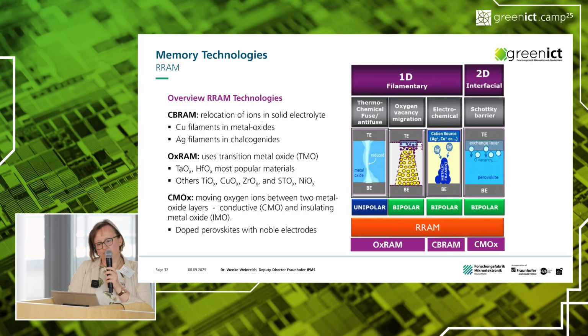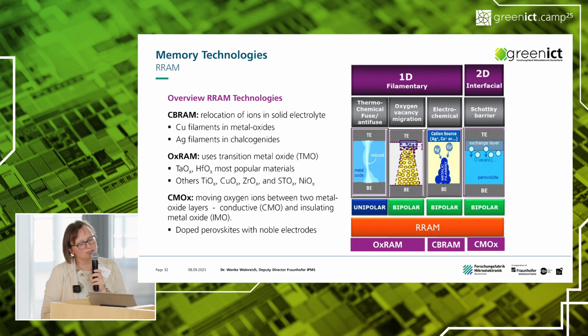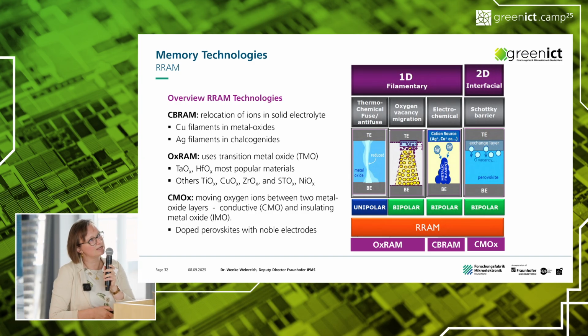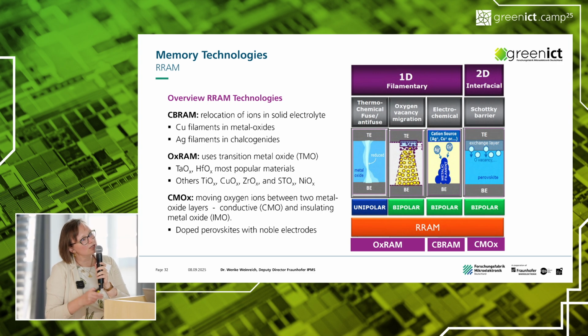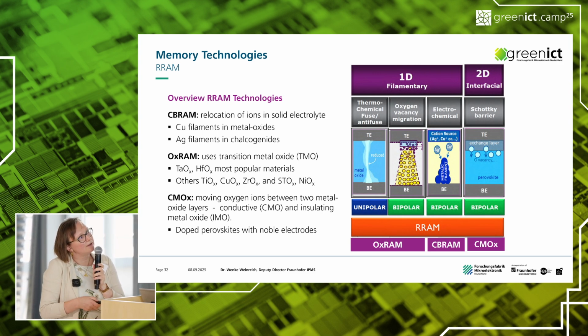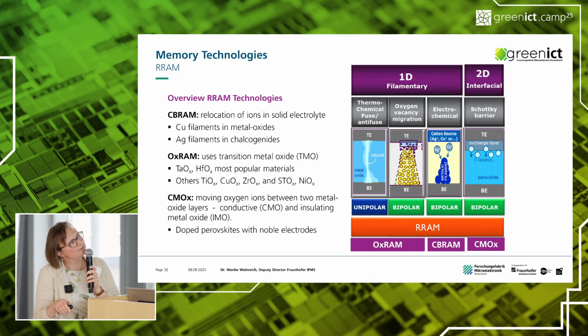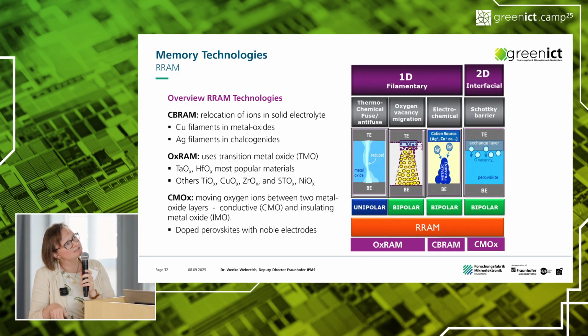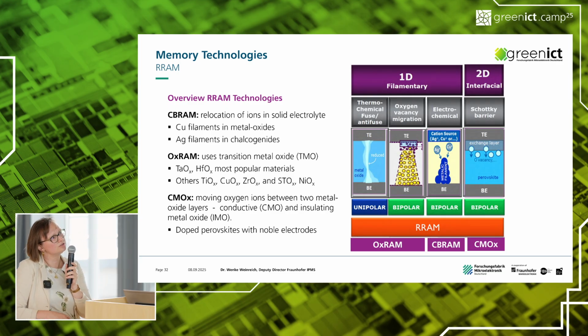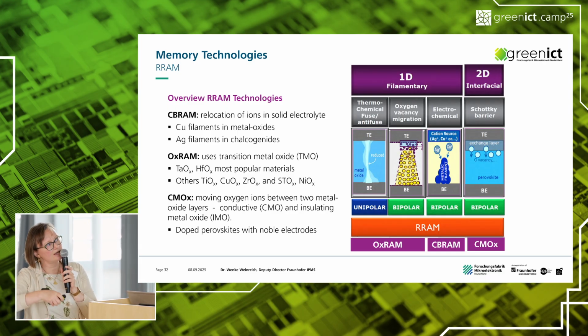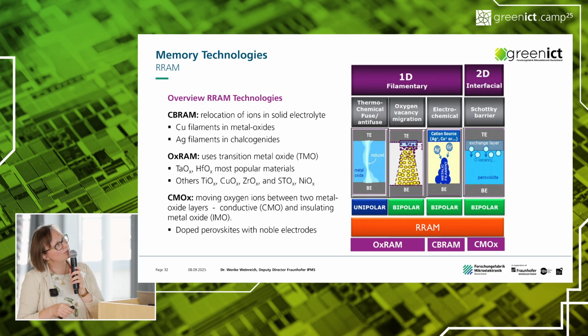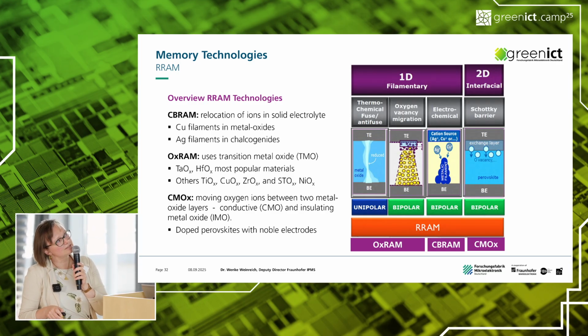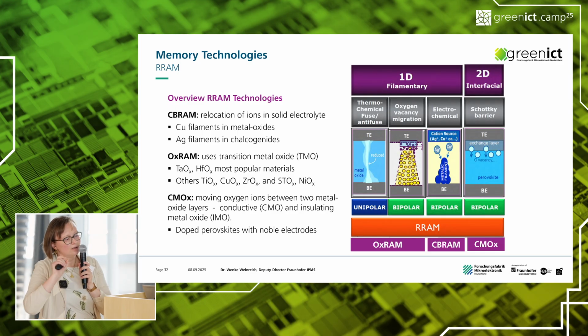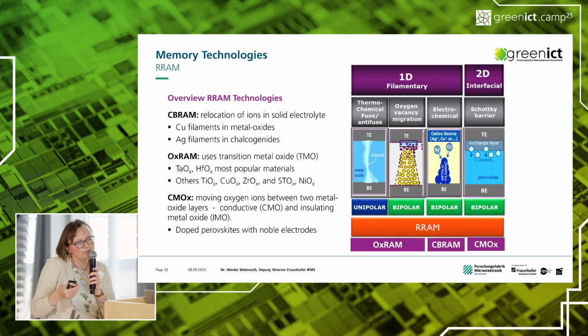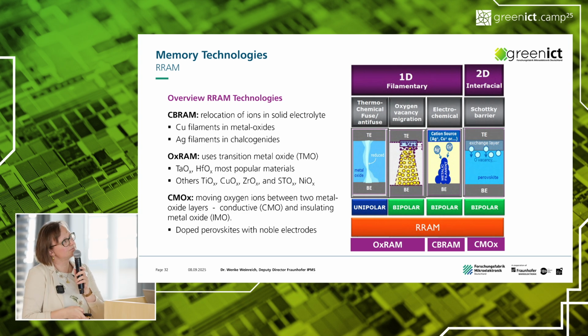Overview, as I said, both are possible. There are a lot of material combinations and mechanisms that bring a so-called resistive switching. One is, for example, the so-called CBRAM, conductive bridge RAM. There you have a base material and you bring a kind of filament inside your stack, which is made of ions, for example copper or silver ions. And just by having the filament or cutting off the filament, you have a high or a low resistance state.